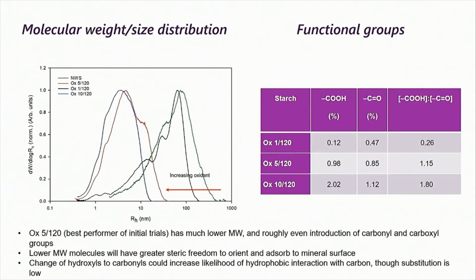For looking at our molecular weight changes, we've used our GPC, of course, and you can see there on your left that as we increase the oxidant, you go from the green of the native wheat starch. The 1% gets a slight little shift; generally the amylose will produce that third species there at around 10 nanometers of the hydrodynamic radius. But at 5 and 10%, a lot of chain scission has occurred. The molecular weight of the material has dropped quite a lot. So if you remember back to what I was showing you for those glucose units, this indicates ring opening and chain scission. So we've decreased the molecular weight of the material quite significantly there.